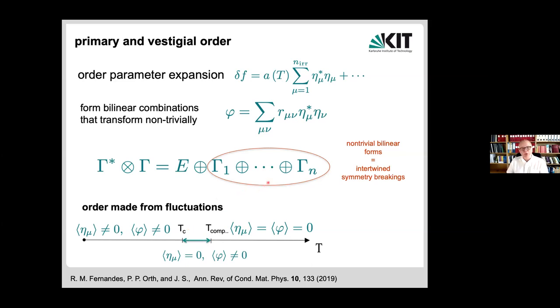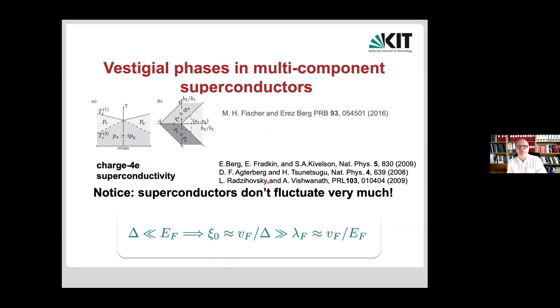Good. Now, with all this in our mind, there was an interesting question of whether one can see those vestigial phases, those composite orders, in superconductors. Not in the sense of the iron-based superconductors, where ultimately what condensed was a composite of the magnetic order parameter, but really a composite of the superconducting order parameter. There was some theory work before we looked into this. On the one hand, Mark Fischer and Erez Berg looked into a potential explanation for the strain dependence of transition temperatures in a px plus ipy superconductor, at that time with the idea maybe to say something about strontium ruthenate, and also charge 4e superconductors can be conceived as composites of charge 2e superconductors quite naturally.